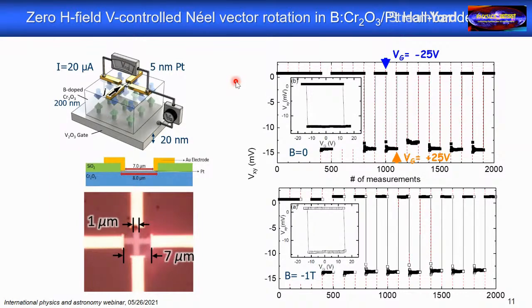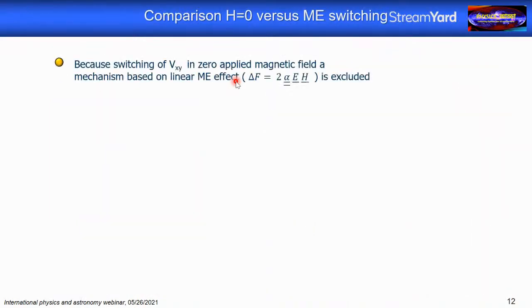And that tells us something. It tells us that the regular magnetoelectric effect, as we know it from pure chromia, cannot be the cause of this switching. Because we know from the linear magnetoelectric effect that a magnetic field has to be present to create this difference in the energy landscape so that you can switch with electric fields. But here we do it without a magnetic field.